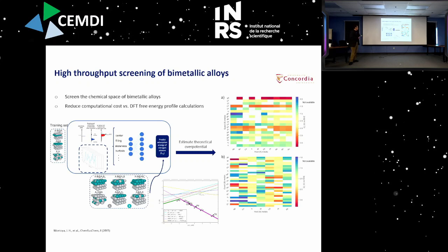from DFT calculations. And so we have a training set here of different alloy slabs with different materials. So this we can calculate. We calculate their electronic properties, such as the D-band model, the D-band features of the active catalytic site. So these are used as our descriptors. We use machine learning in various implementations. The very first implementation was just artificial neural networks, but Mehdi can tell you that he's moved on now to more elaborate methods. But anyway, the idea here is that our target is to predict the adsorption energies of nitrogen